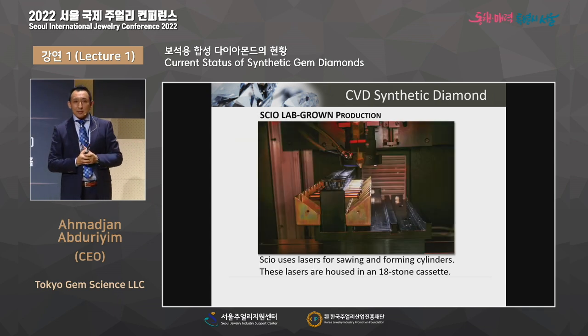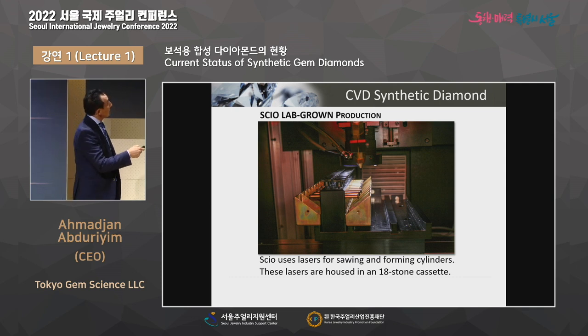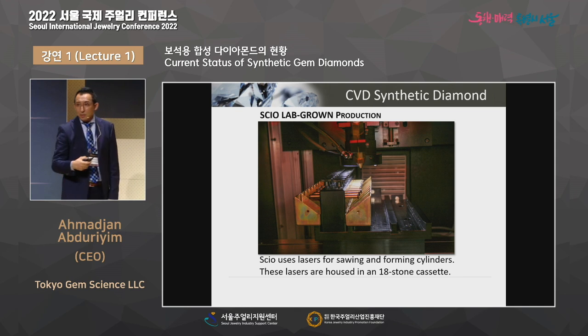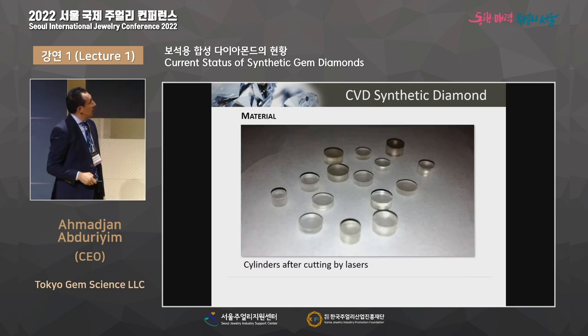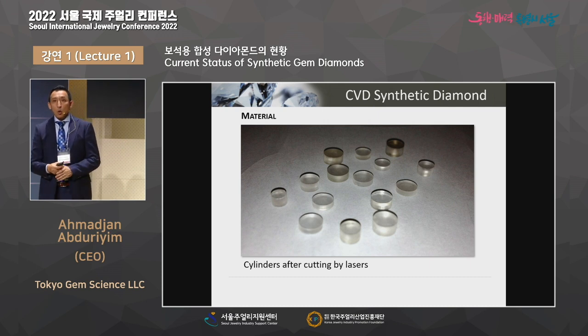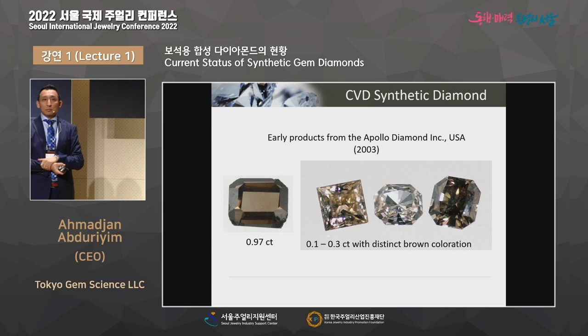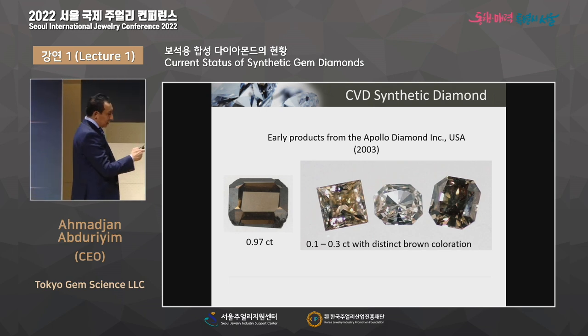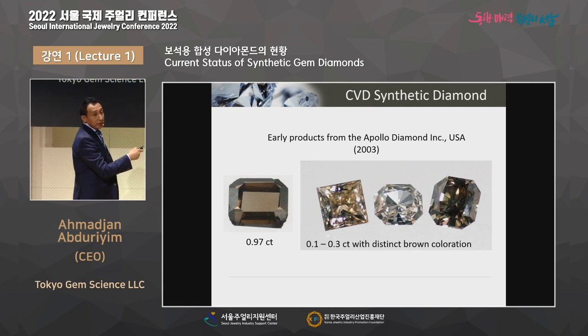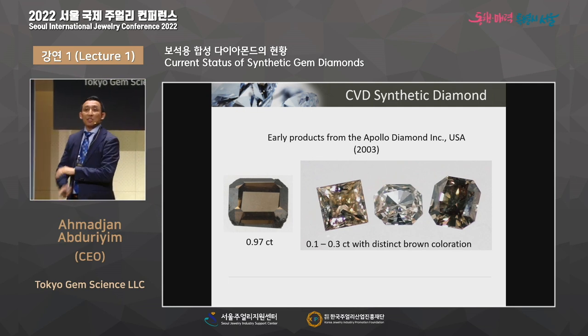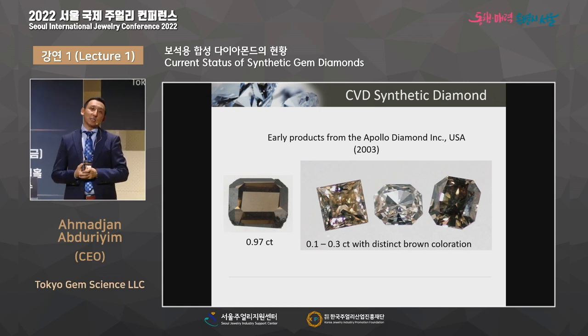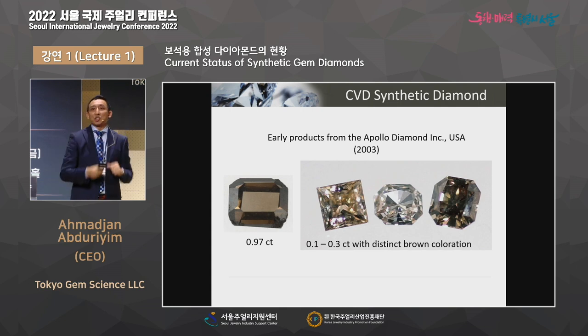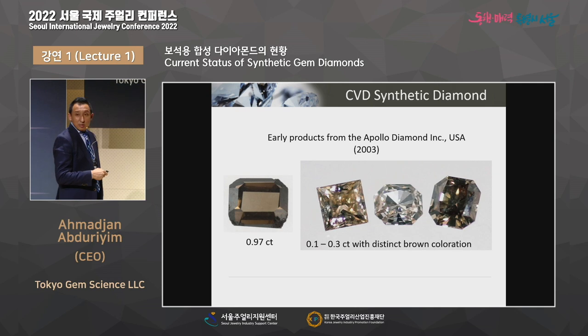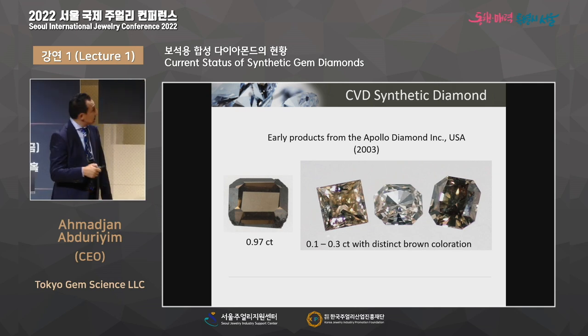And how can we use that? All right, we put the CVD diamond here, and we have a laser beam just cutting it to make a cylinder. Then we polish that to make this kind of synthetic diamond. However, the first market appearance was from Apollo diamond in 2003. We see the first brown CVD diamond on the market. Brown is not really welcome. However, it takes just 5 days to create the CVD diamond and is much more economical than HPHT grown. And the size is 0.1 to 0.3. It's not so big.